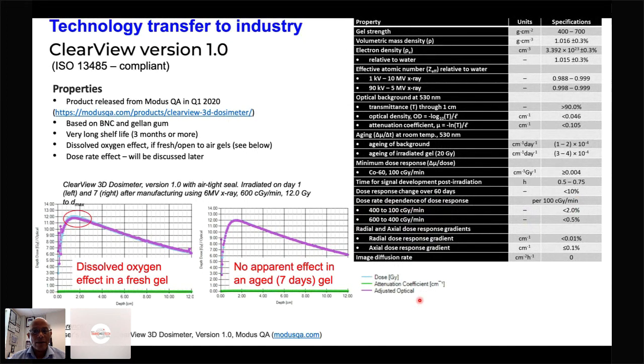So what came out of that is some years back, we were able to transfer this technology to the company Modus Medical Devices. They recently changed their name to Modus QA, and you can see the website down here. And we actually licensed two different hydrogel systems with two different tracer molecules. One was a gelatin-based gel cross-linked with glyoxal, and another one was gellan gum, and the radiation tracer molecule is a tetrazolium molecule. And so they have been doing their own pilot trials. We assisted them to scale up the synthesis or the preparation of the hydrogels and the cross-linking and all that. And they have done their own industrial tests, and recently they launched this product as an ISO 13485 compliant product.